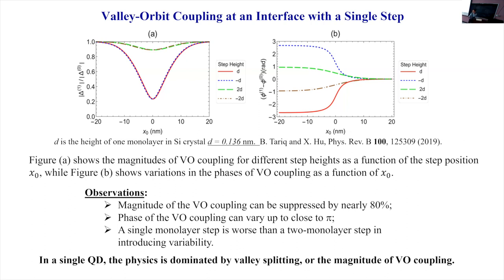I remember several years ago, Jason Petta's group, one of the leading experimental groups studying these spin qubits in silicon, made a 12 quantum dot sample in silicon germanium. But their particular interface was relatively slowly varying in terms of the gradient from silicon to silicon germanium. So instead of a sharp interface, they have an interface that is several angstrom thick. Out of the 12 quantum dots, 3 act as sensor dots, so there are 9 active qubit dots. Turns out more than half of them, they couldn't detect any valley splitting. The splitting is so small, it's just not within the resolution of their experimental technique to differentiate the two valleys.